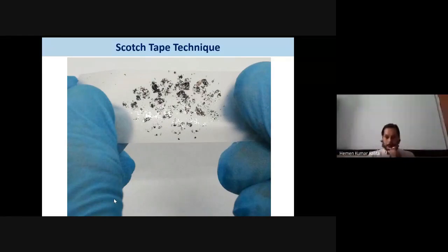If you see in the slide number 11, I suppose, there is a piece of Scotch tape, and on the Scotch tape they have taken flakes of graphite. They keep peeling off with the Scotch tape until the thickness of the graphite becomes very, very thin. They peel off, and then again they peel off, and they continue this process until the graphite becomes very thin. Now if you take that peeled graphite under a microscope, then if you are lucky, you might observe a single layer or maybe a bi- or tri-layer graphene.